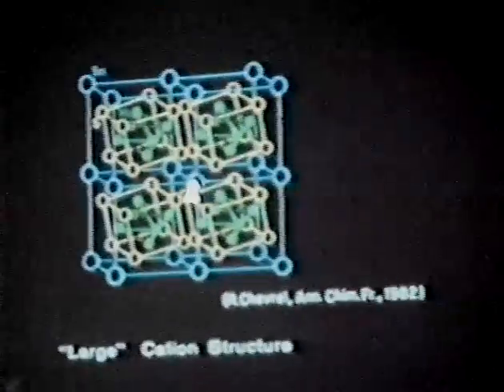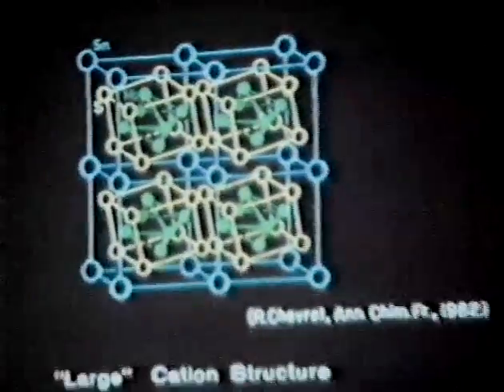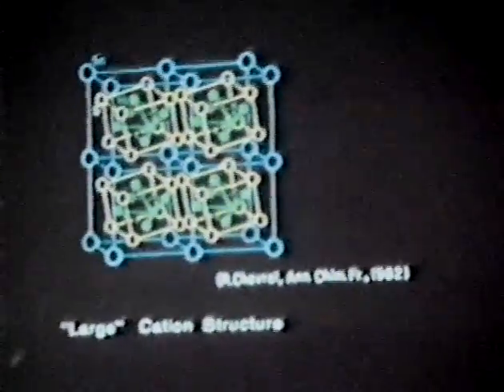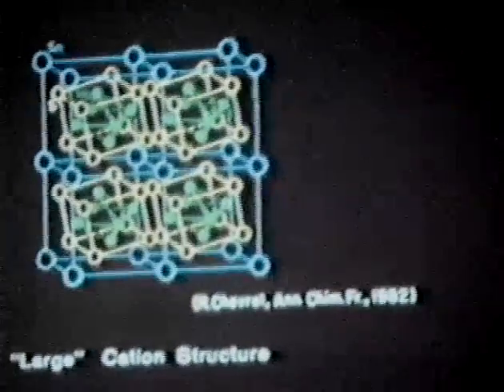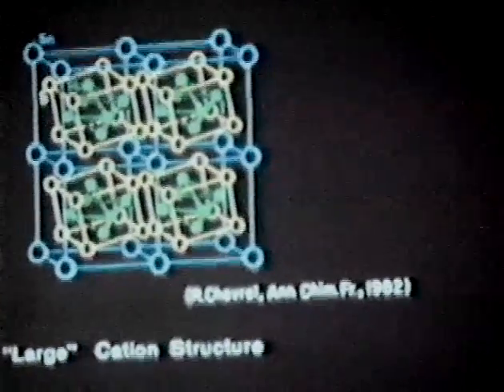These large cation structures, the large cations or the ternary metals here in blue, are pretty much localized, and this gives great stability to the structure. In fact, all the Chevrel phase compounds really are very stable because of this. The molybdenum-sulfur bond distances are relatively short, and the structures are therefore rather stable materials.